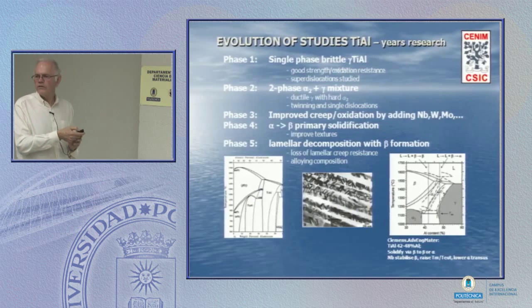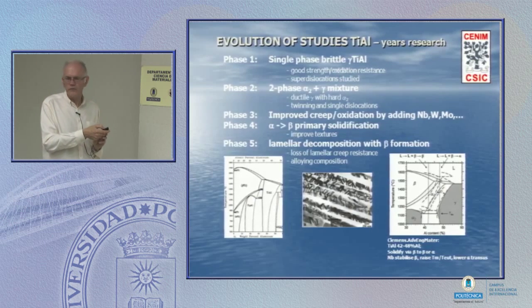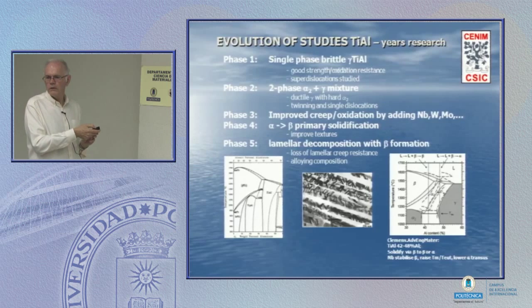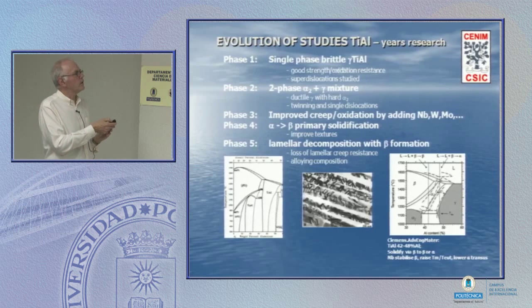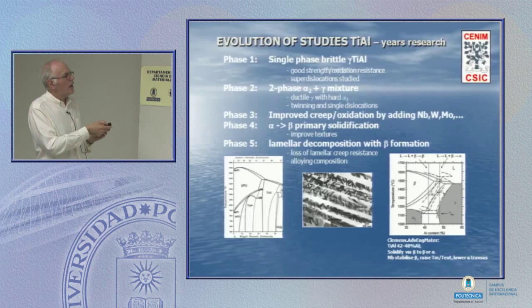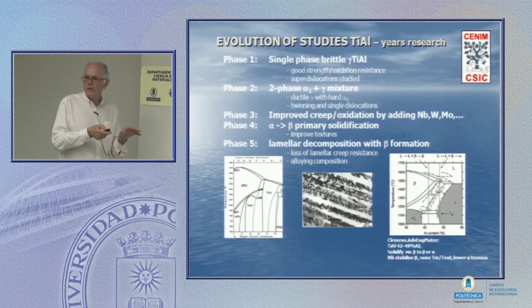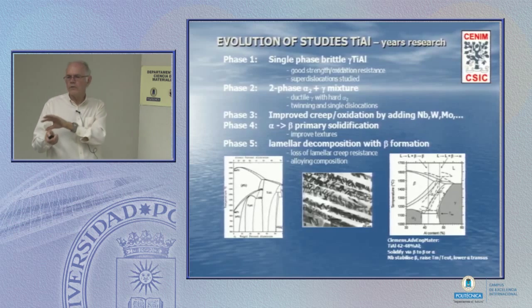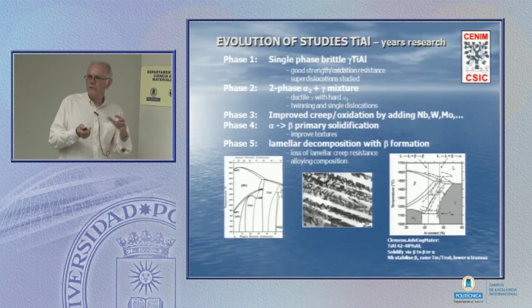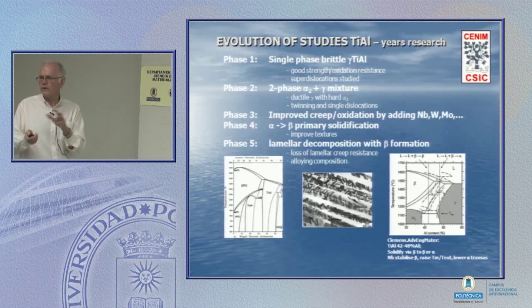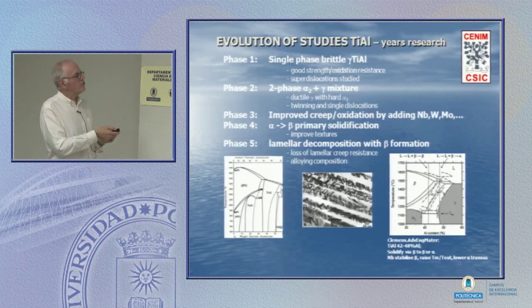So over the decades, there have been a number of phases or stages of research development. The very first phase said, let's have a look at TiAl, single phase. It's very brittle, even though it's got some properties, very brittle. So we jumped very quickly to this alpha-2, alpha Ti3Al plus gamma TiAl mixture. And as in a composite, we get ductility from the one phase, we get strength from the other, and we mix the proportion of the two according to how much ductility, how much strength, how much toughness do we want. Then we need to improve creep and oxidation, so we add these BCC metals.